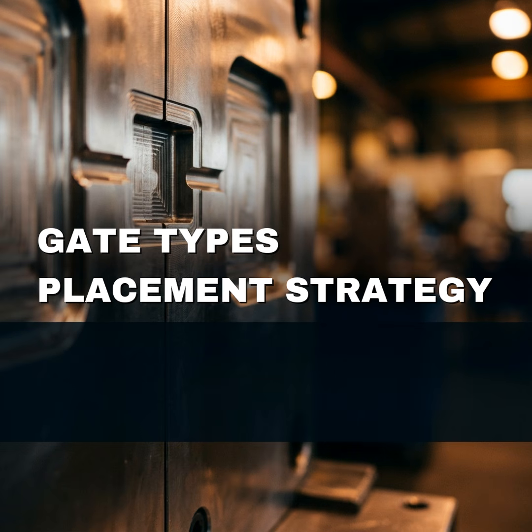So you typically use direct gates for large, thick-walled parts. Think big pots, TV housings, or for plastics with high viscosity and poor flowability, like PC or PSF. That makes sense. So, for parts where appearance is critical or they're thinner, you'd need something different. What's another common gate type?